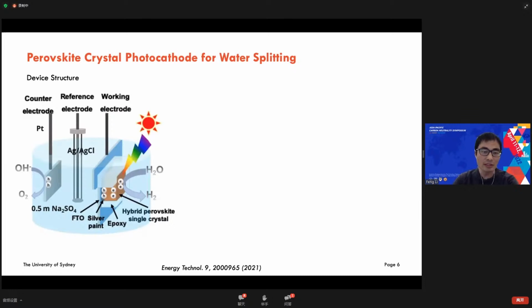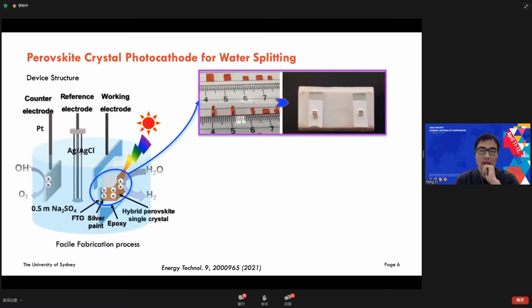So it's quite easy. This is our first work on using perovskite materials as an active layer for water splitting. We just fabricate the single crystals and use silver paint to contact the single crystal with the active substrate.